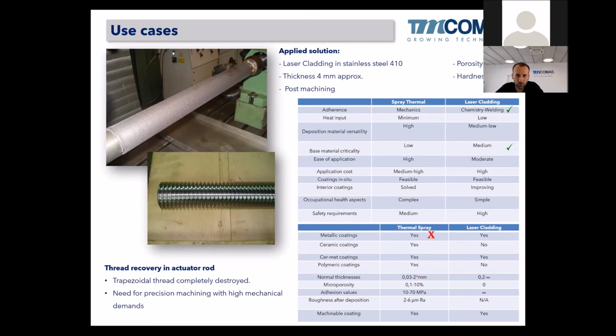So we had to clad. And we clad a stainless steel 410 because at that moment we didn't have any heat-resistant steel available at the workshop. So the only material that we could apply was martensitic stainless steel, which is also heat-resistant. So we applied a coating. We needed a coating that could be machined. We must machine a thread in the coating, so the only way to do that is by cladding.